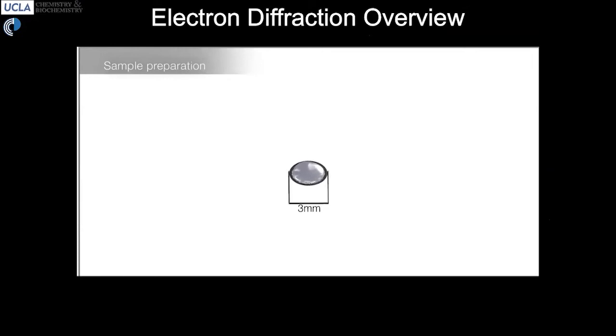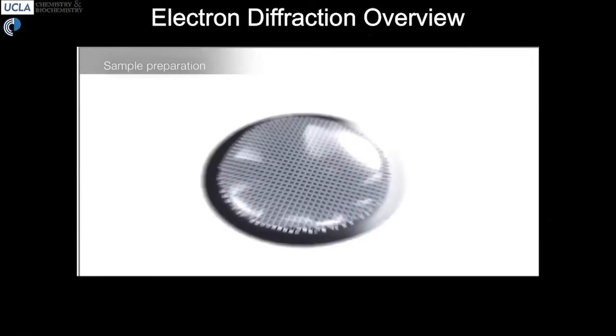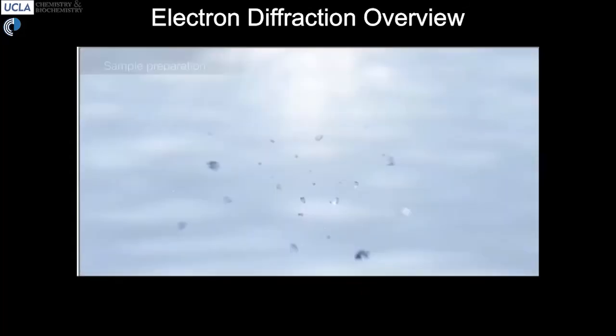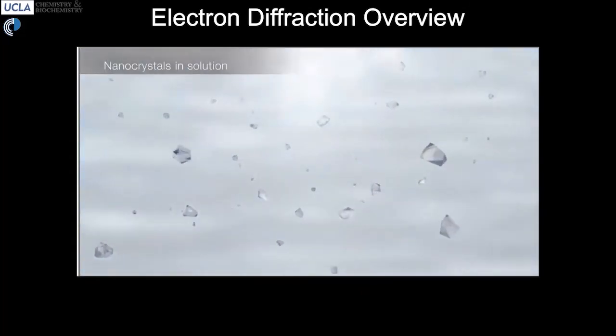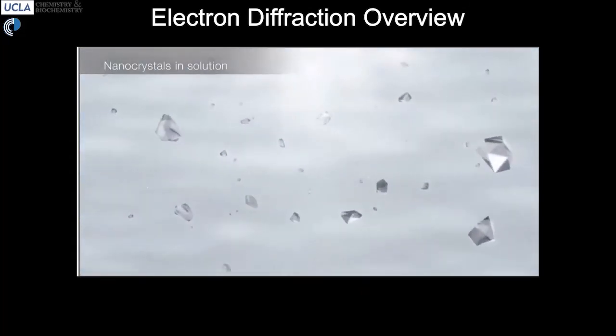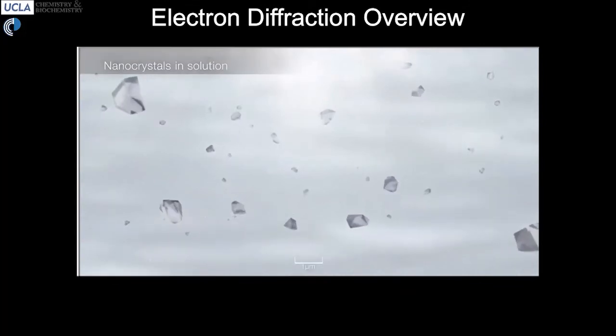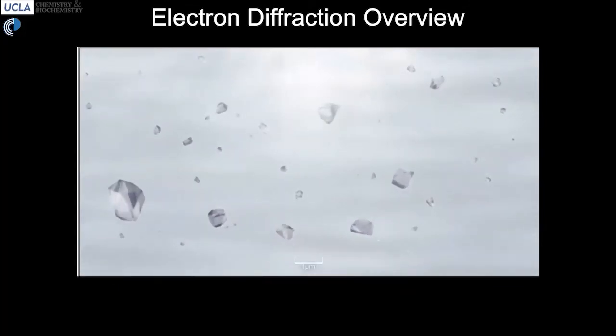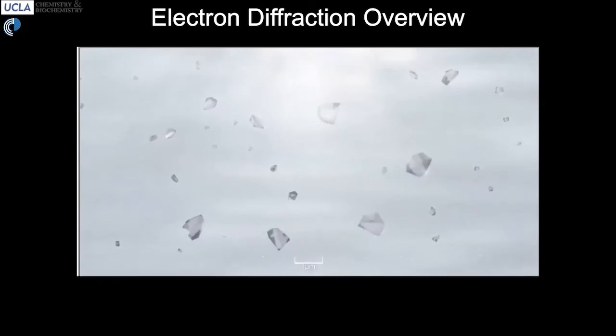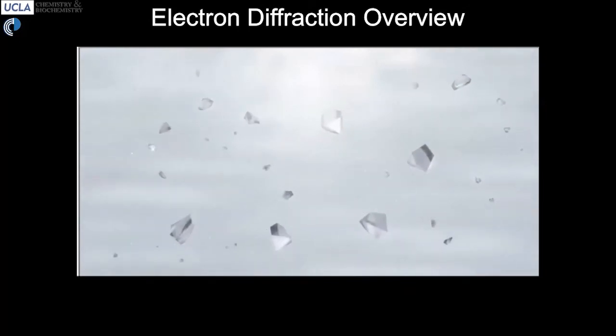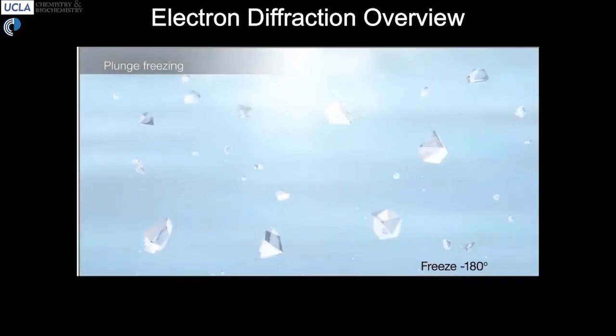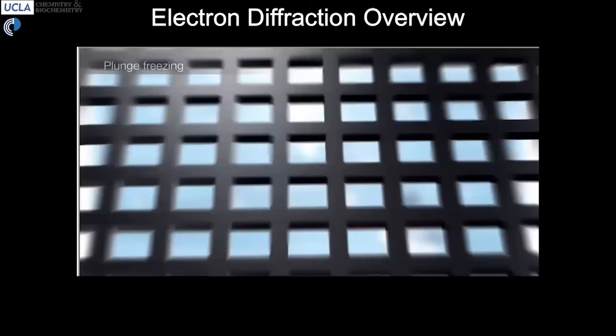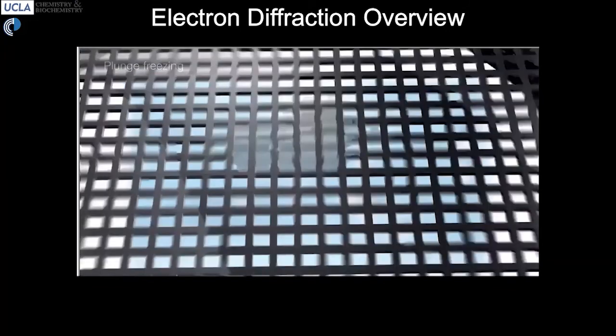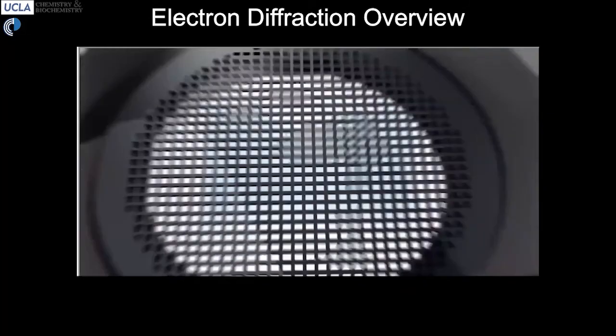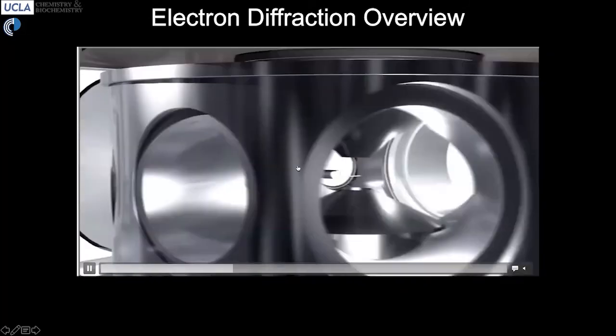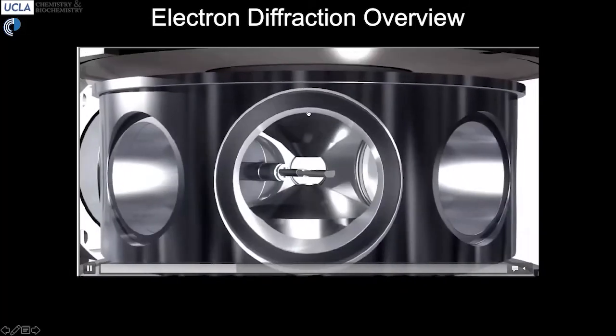Well, a sample can be in solution. It can be tiny crystals found in a solution, or it can be crystals found in powder. In any case, it's any situation where you might find an ordered array of molecules at the nanoscale or microscale. When these are present in solution, you would put them on a 3 millimeter wafer. You could either freeze them or dry them, or simply deposit them onto this wafer, then put them using this holder into the TEM.